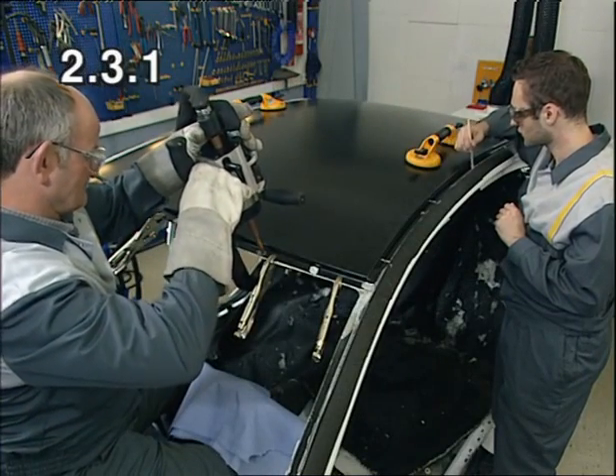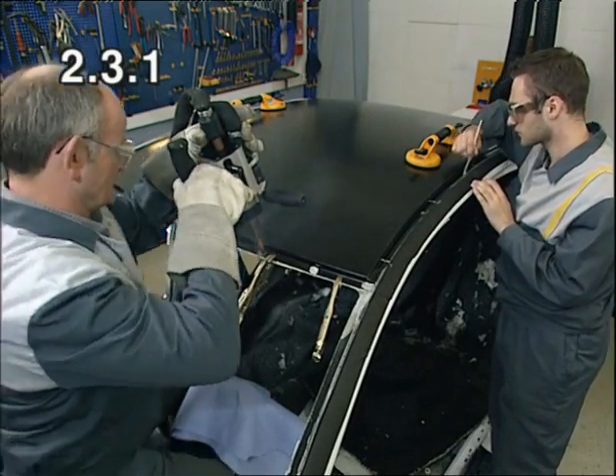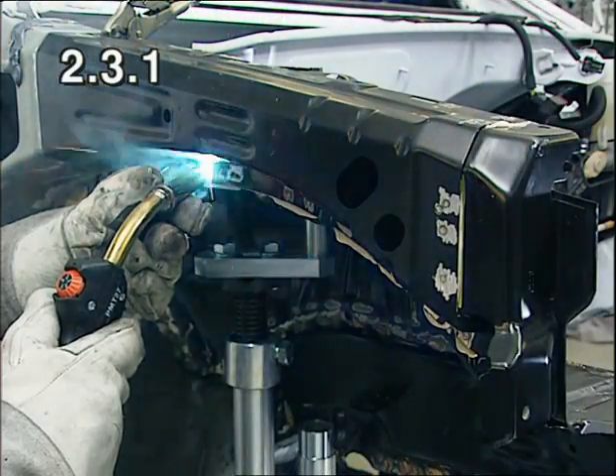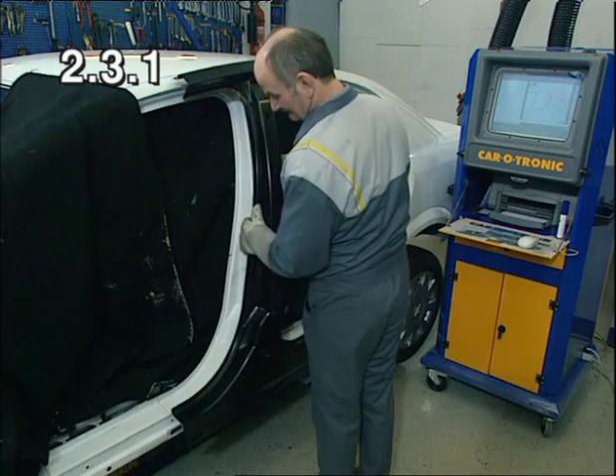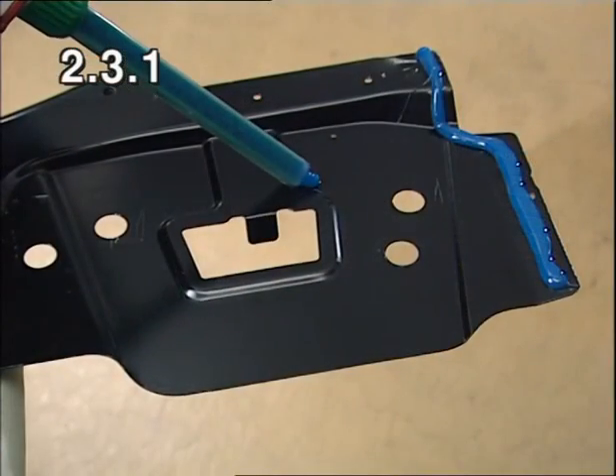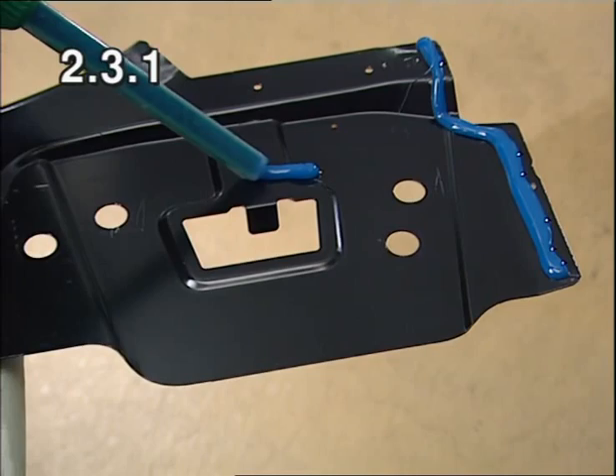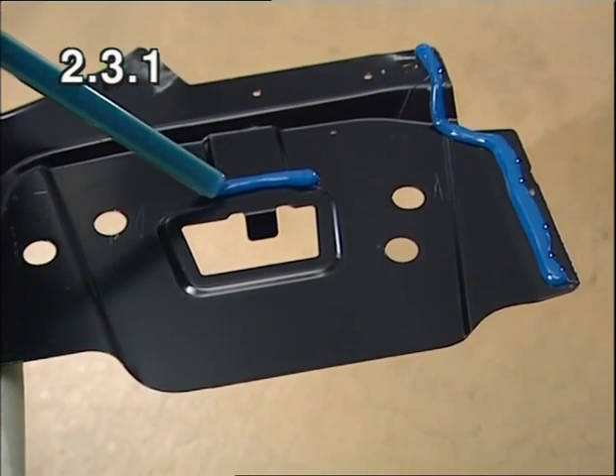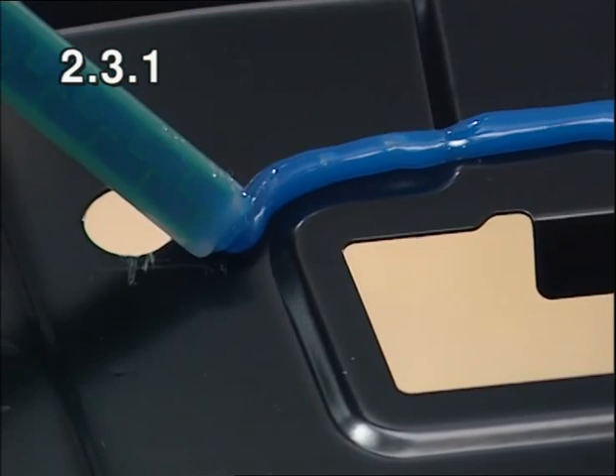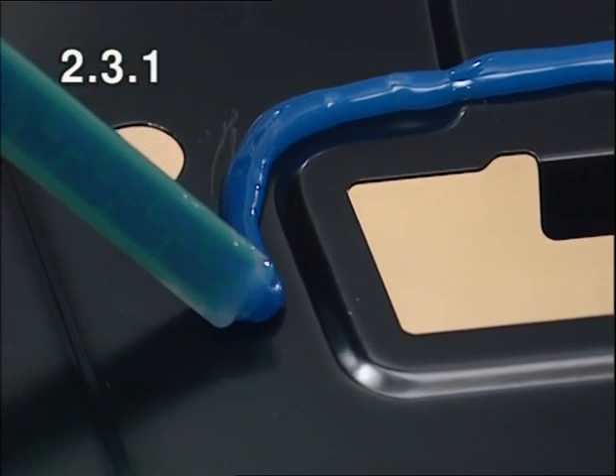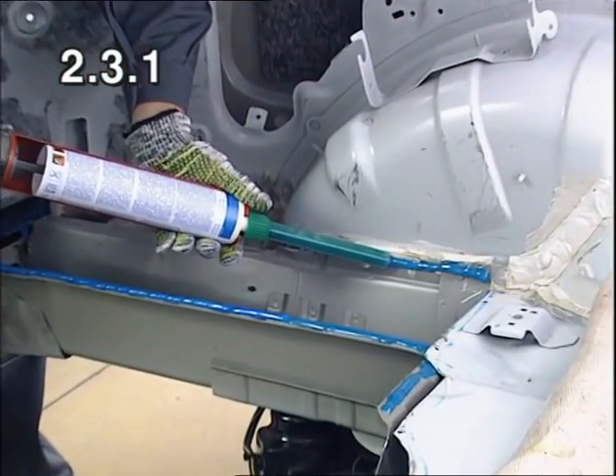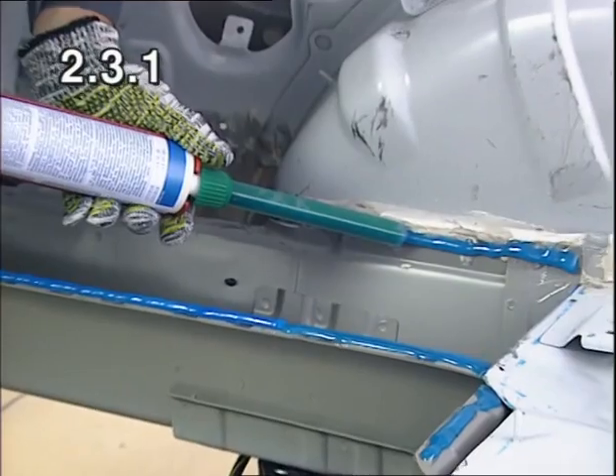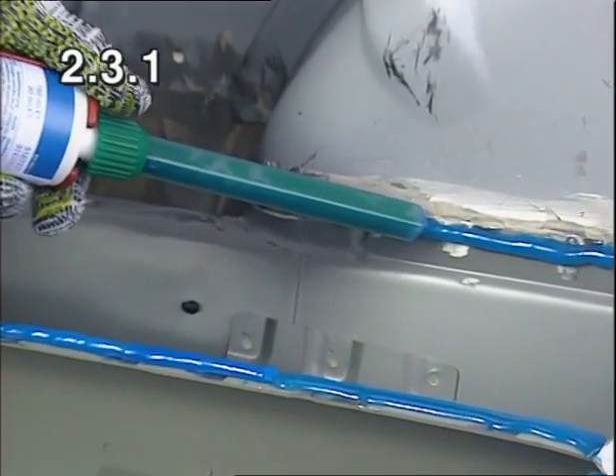Further areas of application are the laser-welded roof, parts of the front of the vehicle, and the outer rear quarter panel. Further advantages of using a body adhesive are good tolerance compensation and optimum corrosion protection in the flange area. The system has outstanding bonding characteristics on coated sheet metal repair components, high alloy steels, and pre-treated aluminium. Compatibility is guaranteed with the majority of sealants and sealing materials, and with overpainting using conventional paint systems found in the repair sector.